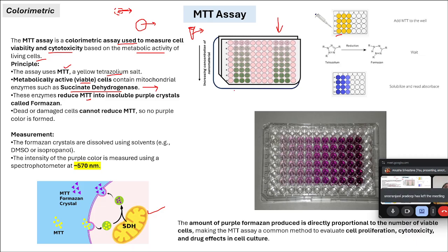Now suppose this is the plate, you do it in triplicates, okay? And this is coming down, increase in concentration. Suppose this one is control, and then 5, 10, 15, 20, 25, 30, 35. Suppose this one is 35 microgram per ml. So with increasing concentration of nanomaterials, you treated the cells. This diagram is made only to make you guys better understand. Now different dilutions of this nanoparticle suspension are added to the cells that are already grown in this 96 well plate.